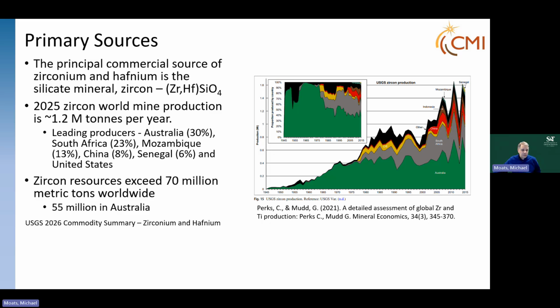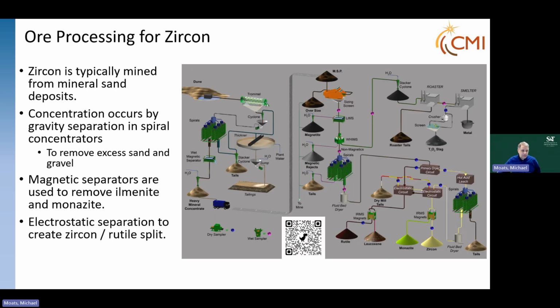Most of the zircon in the world is produced in Australia, and they also own most of the reserves. You can see that it's bounced around over the years, but basically zircon comes out of Australia, and it comes from mineral sand deposits. Mineral sand deposits are essentially beach sands, so they can be along an existing ocean, or they were part of a shoreline at some point. They contain lots of heavy minerals, so we separate the minerals and make a concentrate using gravity separation, which are the spirals right here. Then we use magnetic separation to remove things that are magnetic, such as ilmenite and monazite. And then we use electrostatic or high tension separation to recover zircon and rutile.